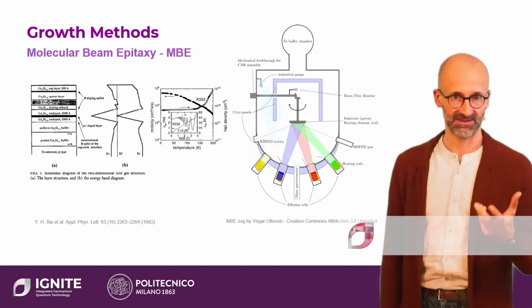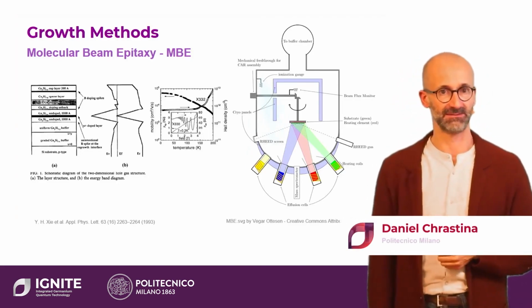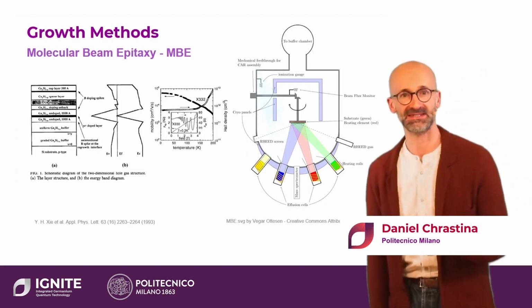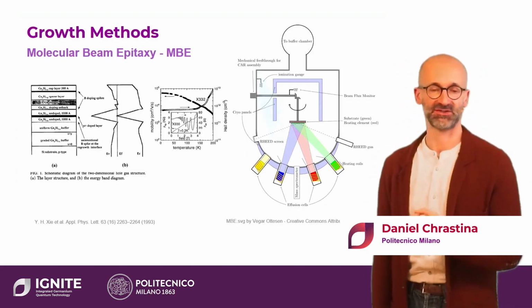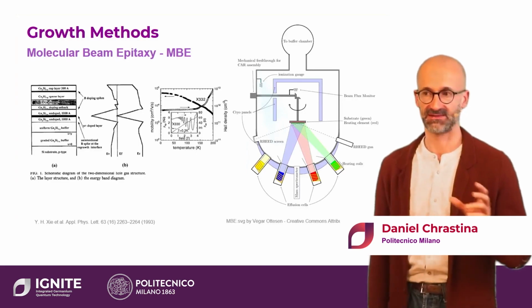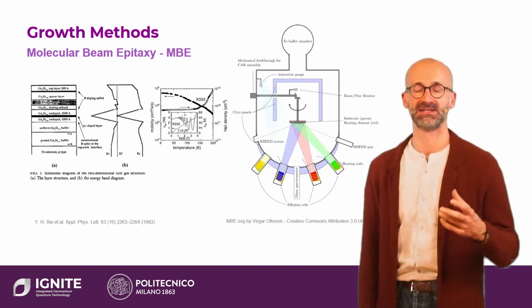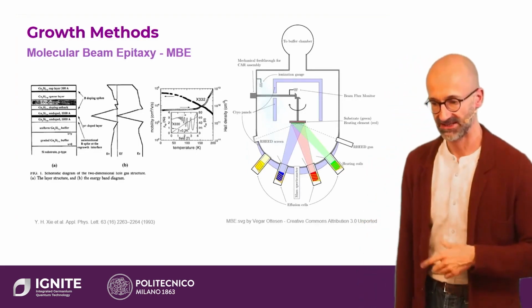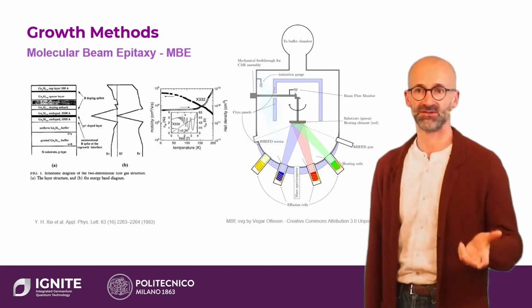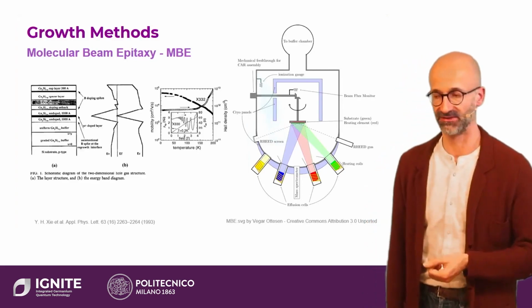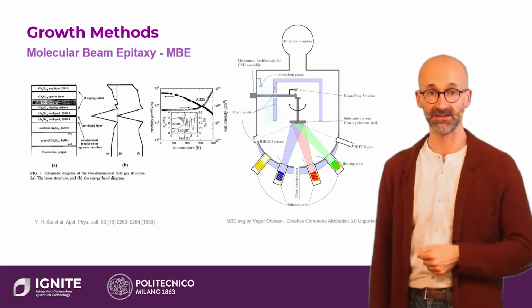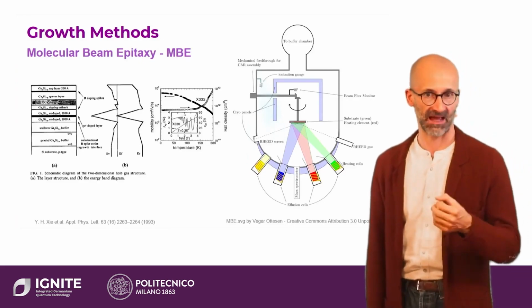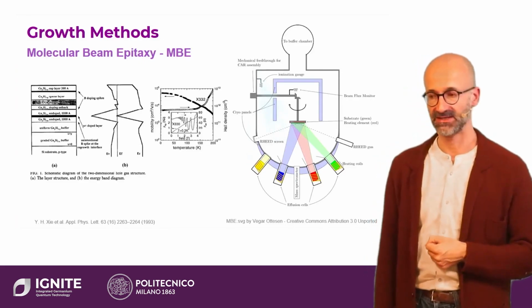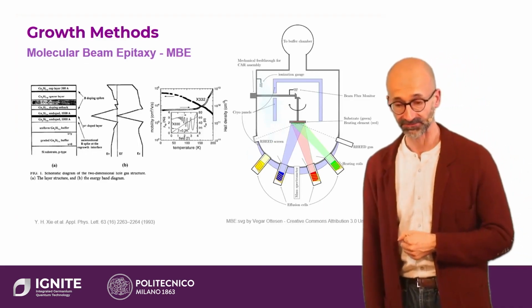Historically, germanium and silicon germanium were first grown by molecular beam epitaxy. This is a system in which essentially the elemental semiconductors, pure silicon and pure germanium, are placed inside a vacuum chamber. They're heated. Usually silicon and germanium are heated up by electron beams, although some other elements can be heated thermally, until atoms are basically subliming off the solid material into the vacuum chamber.